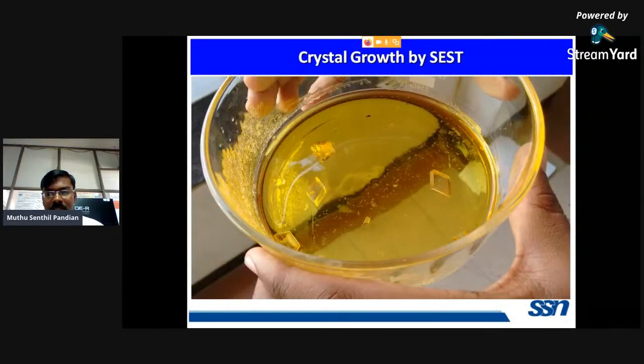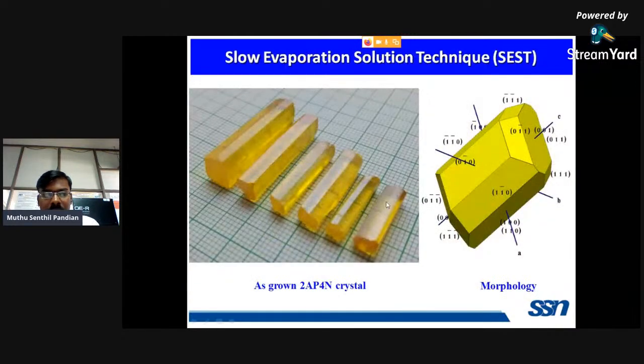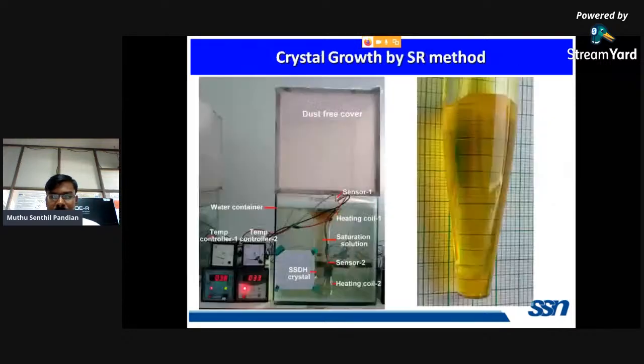Normally in the conventional method, the crystal is grown like this, with several growth sector boundaries appearing in the conventionally grown crystals. The dislocations originate from the growth sector boundaries. That is one thing. Another thing is that because of the several growth bands and growth sector boundaries, impurities accumulate in the conventional method grown crystals. We have used materials recrystallized several times. Even so, some impurities always appear in the prepared saturated solution, which naturally affects the crystalline perfection.